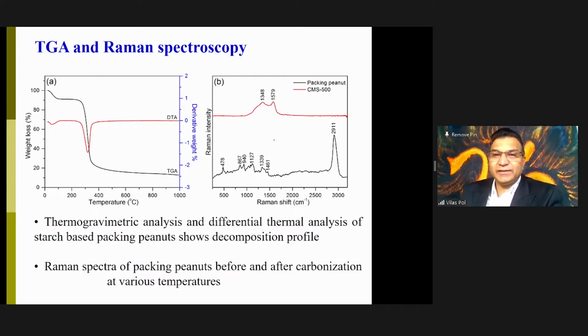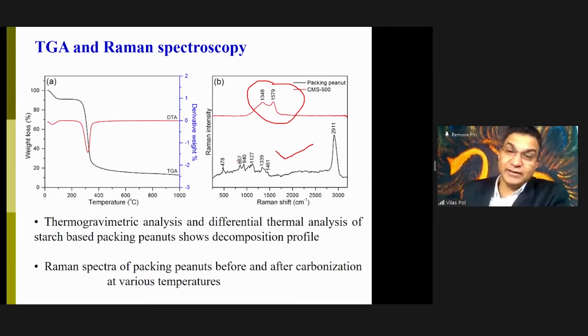Then we characterized it to understand exactly what is happening. So this is a Raman spectroscopy, which tells you what kind of carbon you have fabricated. And it tells that it is a disordered form of carbon fabricated at a lower temperature. This was the original packing peanut Raman spectra that has many bonds, the bonds coming from the stretching frequency. And that's why we have multiple peaks here. But eventually it modified into only a simple 2 peaks. That is a signature of graphite. It has a huge loss because starch has mostly water and around 28% solid. So we remove the water at lower temperature, and this is the solid material we have left over.